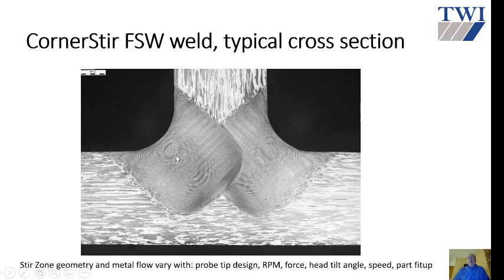You see beautiful uniformity, minimal heat affected zone, and this whole geometry changes tremendously with probe design. The RPMs are pretty high, by the way, 4,000 RPM with the probe tilt. But again, the shoulder amazingly only maintains the shape. It's only pushing down. The downforce is fairly high, actually, 7,000 Newton. The tilt angle of the torch is important. Speed is important, fit up is important. We're doing on the project right now, for instance, on lap joints, dissimilar joints, 4 meters a minute. TWI already accomplished 6 meters a minute in that. So it is an amazing process.